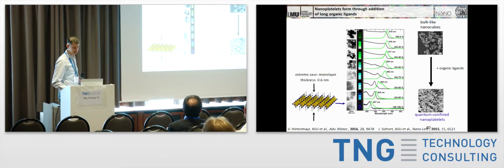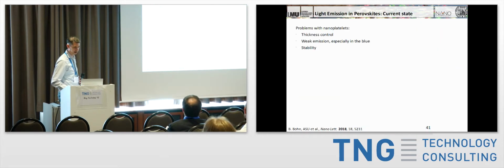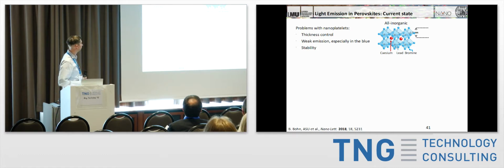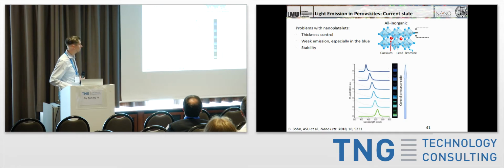And so that leads to these broad spectra that we're seeing in there. And also the efficiency in the blue is quite low, and the stability on substrates was quite weak. And so there we replaced then the organic ligand, organic molecule, with cesium, and now we were able to control the precursor ratios a lot nicer.